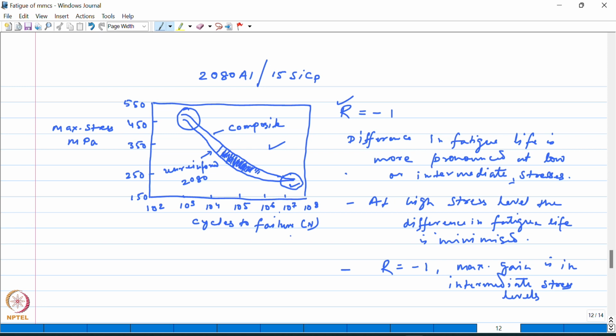Okay. So because of this, the number of cycles that can be accumulated in the low cycle fatigue region is limited. Okay. And therefore, at high stresses, although the plastic strains are lower in the composite, due to the lack of cyclic ductility, the resistance to the cyclic strain is low, and this leads to the convergence of the fatigue lives, as you could see. Okay. So there are two competing factors here. One is the low plastic strain, which will improve the fatigue life or reduce the fatigue damage in the material. But on the other hand, the ductility in the composite is lower, which will actually limit the strain to fracture and lead to an early fracture, right?